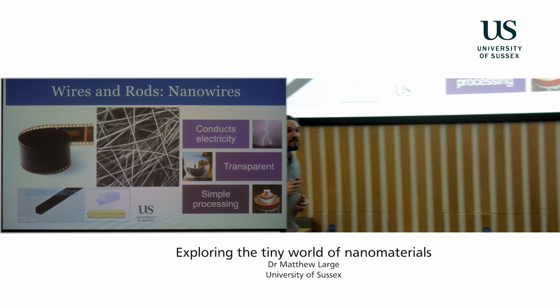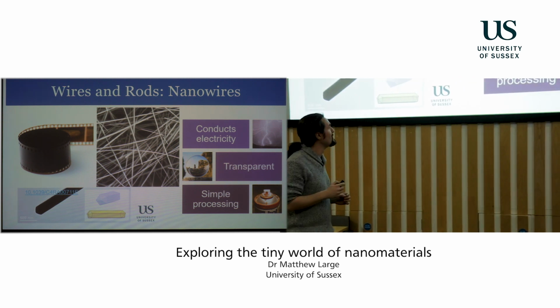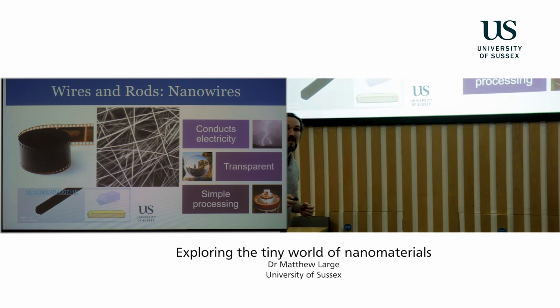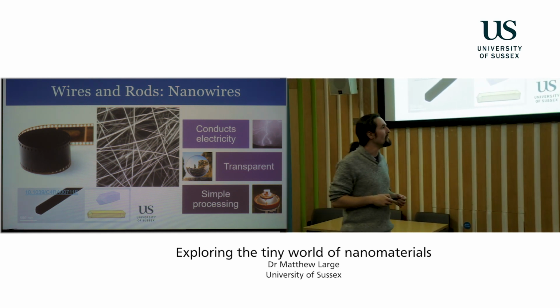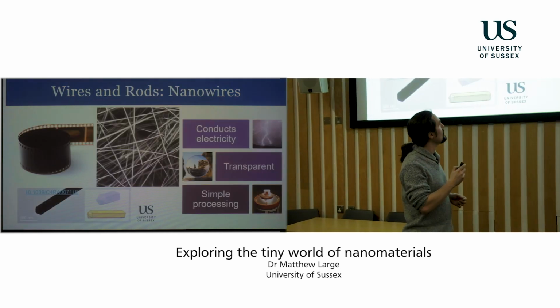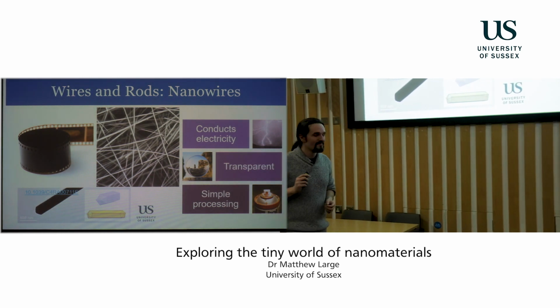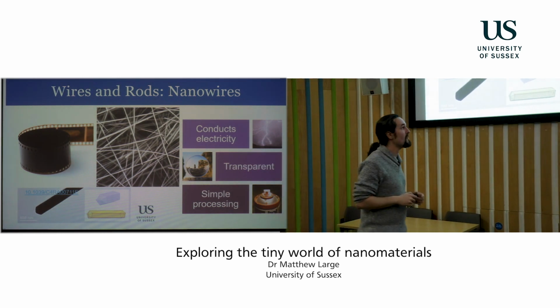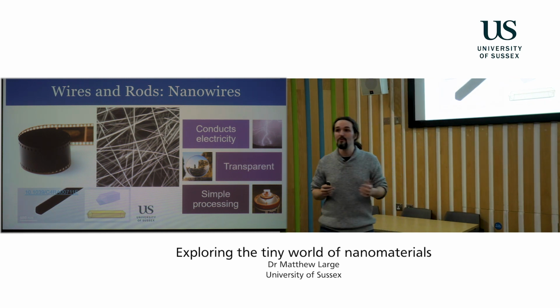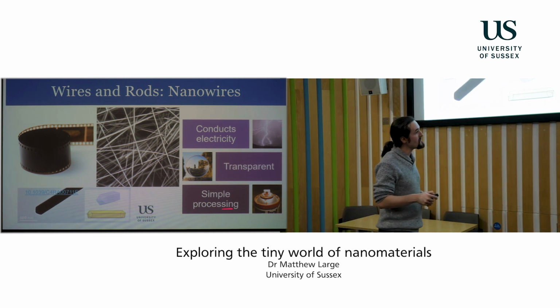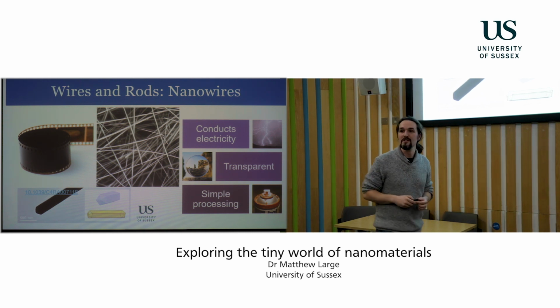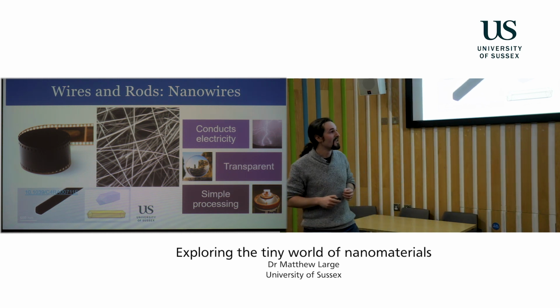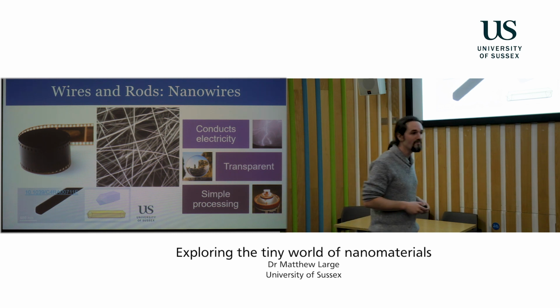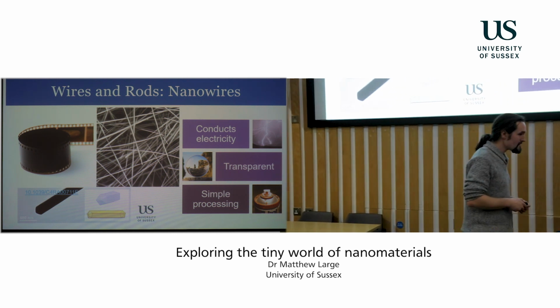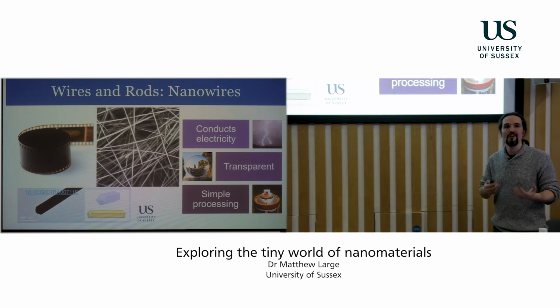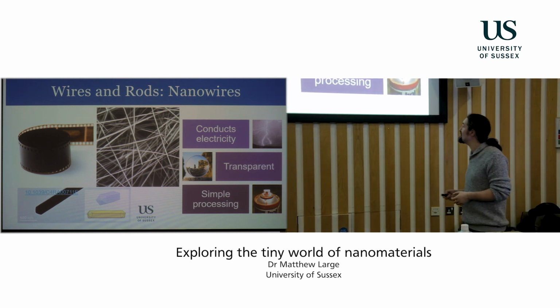Now these have some very neat properties from an applications perspective, and I'm an applications sort of person. Just like graphene, they're very, very conductive. They're actually more conductive than graphene because these wires are made of silver, so they're as conductive as silver. They're also, whoa boy, they are also almost completely invisible. They're very, very transparent because they're so thin. They don't really interact with light. And the processing, how we can use these to make things is really, really simple. Because they're in liquid, I showed you a bottle of the ink, we can paint them, we can spray coat them, we can do all sorts of things. All at room temperature, all using very nice, friendly solvents like water.